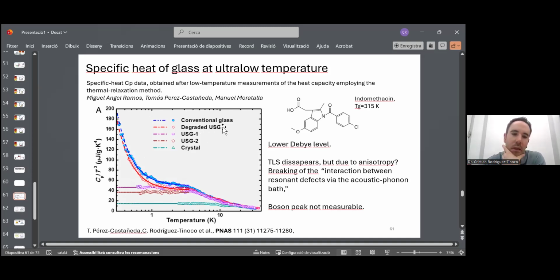Now, here we have this degraded USG, which means this is a USG after some time, after which the glass has absorbed some water. When the system was degraded, with some water inside, then we again observe these two-level systems, the same as in conventional glass.